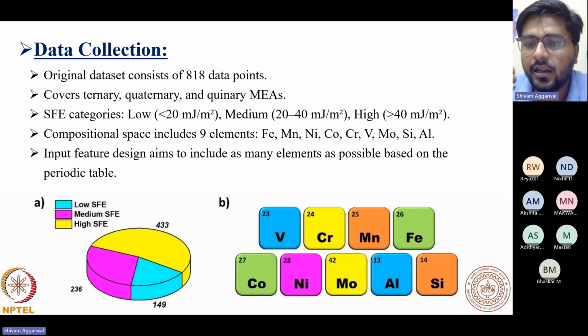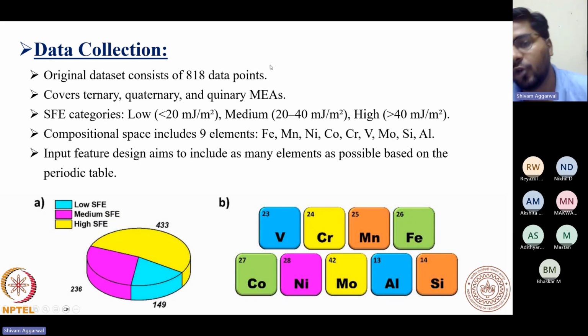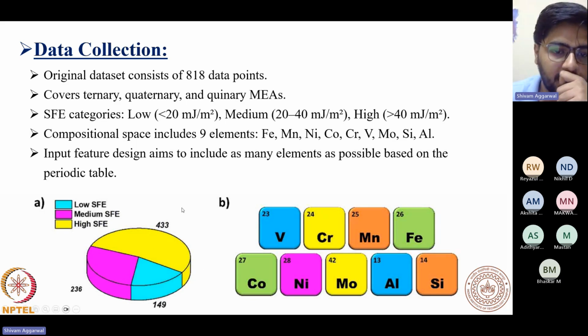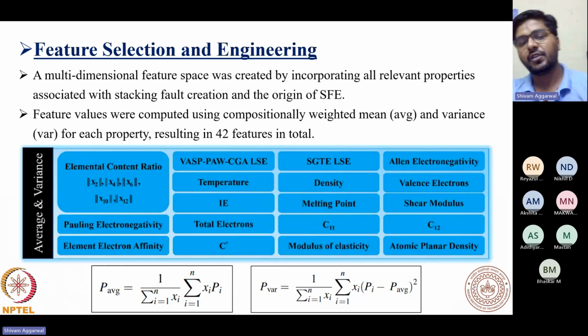Mainly in this data set, only 9 elements are included: iron, manganese, nickel, cobalt, chromium, vanadium, molybdenum, silicon, and aluminium. And if we distribute this data, we can see there are 433 points for the high stacking fault energy, 236 data points for the medium stacking fault energy, and 149 points for the low stacking fault energy.